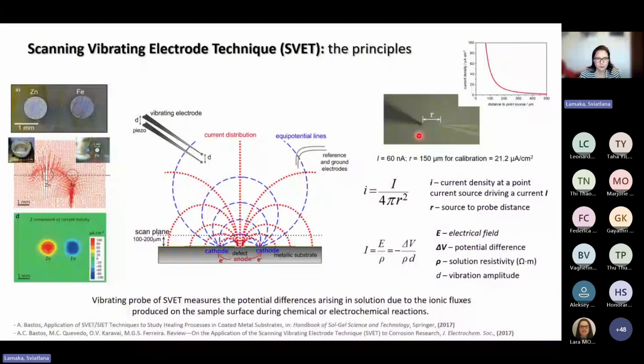This is an example of a PEO-treated magnesium sample. We continue Federica's topic of PEO-treated magnesium. In this case, it's the E41 alloy treated with PEO and also loaded with corrosion inhibitors, or this is a reference sample that is unsealed, also with a thin sol-gel film. We made defects in this coating, and then we started SVET measurements, and we clearly see outbreaks of corrosion activity. Here we compare this reference sample with the one containing corrosion inhibitor. By looking at the peak value of current density, we compare the activity of the sample and how it activates and then decreases with time.